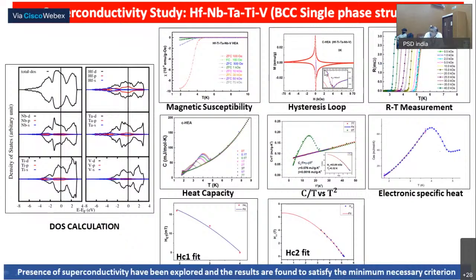That once it forms superconductivity, it does not distort. It remains over there. And all the calculations done on the heat capacity and others have shown this actually follows the entire BCS theory. That is, it shows the same tendency of forming the Cooper pair by phonon coupling, and it also shows that electronic specific heat takes the hump. And all these calculations show that your SC temperature, if you start looking, crosses more than 8K. Now, in a low temperature metallic system, which is not intermetallic, this is one of the highest SC temperatures which has been formed in any superconducting materials.